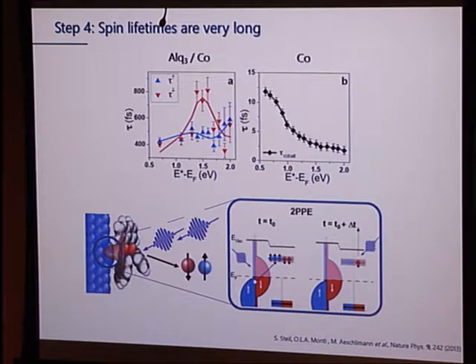When we extract that and measure the spin-resolved lifetimes of that excited molecular state, which accepted an electron from the cobalt, here's what we see as a function of energy. As we scan across the different energies, this is roughly where our hybrid interface state is. You see that the lifetime of the spin-up state is about 400 femtoseconds, and that of the spin-down state is almost twice that, 800 femtoseconds. And you might say, well, that's short, and that's nice, but so what? Well, in cobalt, I do that same measurement, and the lifetimes are like 10 femtoseconds or less.